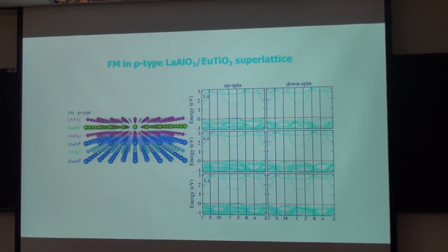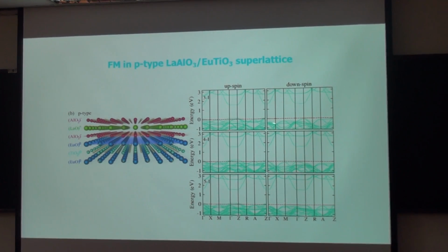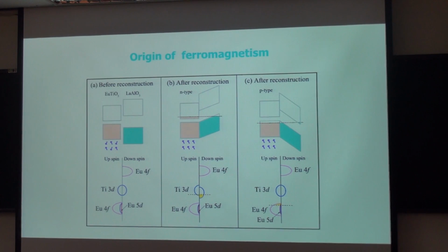And for the p-type state, we also find an antiferromagnetic to ferromagnetic transition. But here, the holes mainly reside at the europium electronic state. And we can find the system is fully spin polarized. That is, there's a band gap for the down-spin channel, and for the up-spin, the system is metallic. So we have realized a fully spin polarized two-dimensional hole gas in this superlattice structure.